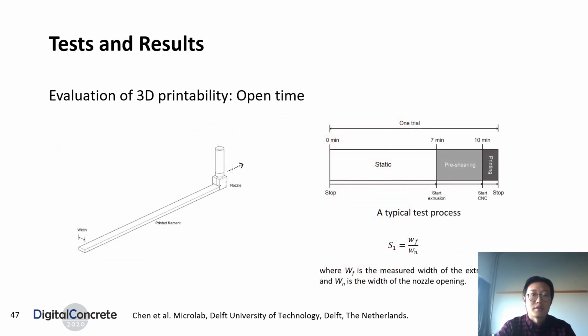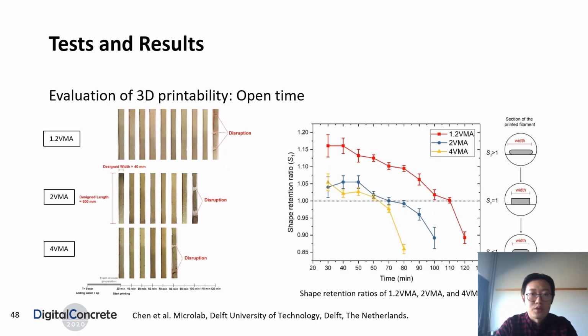The second assessment is the open time. We printed one single filament with a length of 600 mm. The test started at the material age of 30 minutes with a 10-minute time interval, and the test was terminated once disruption occurred. A pre-shearing process is also applied before printing in the time gap. The width of each printed filament is also measured to check the printing consistency. The results reveal that increasing VMA dosage leads to a reduction of open time, but it can benefit the shape retention property.